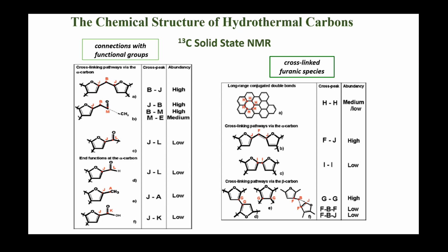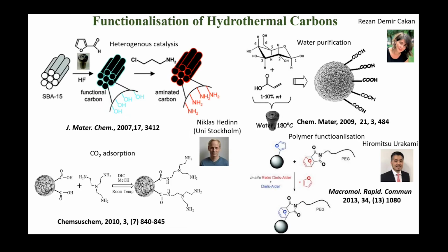5-hydroxymethylfurfural, which is a furan ring with an aldehyde on one side and a hydroxymethyl group on the other side. And so this molecule then starts to condense via all sorts of organic chemistry reactions and then dehydrates to form this furan-rich structure, and sometimes it really forms these conjugated molecules. So that's how the hydrothermal carbonization is happening. Now, again, as you can see, these are very old papers. I just wanted to show that this can be used as a very nice functional material for a lot of different applications, some of which I know are of interest to bp-ICAM, and they're very cheap. So I thought I'd show this older work.